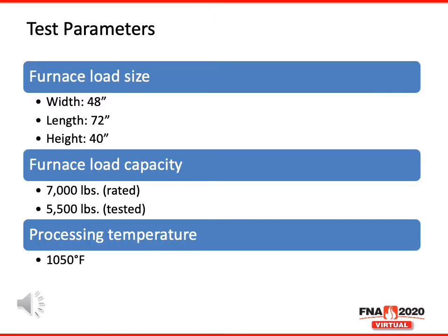Now I'd like to get into looking at the test results from each of the ancillary systems presented. So first I'd like to define some of the test parameters. The furnace load size that was used for these tests was 48 inches wide by 72 long by 40 inches tall. The furnace had a rated load capacity of 7,000 pounds. There was a 5,500 pound load placed in the furnace during these tests. And the furnace was run up to 1050 Fahrenheit prior to the start of the cooling cycles.